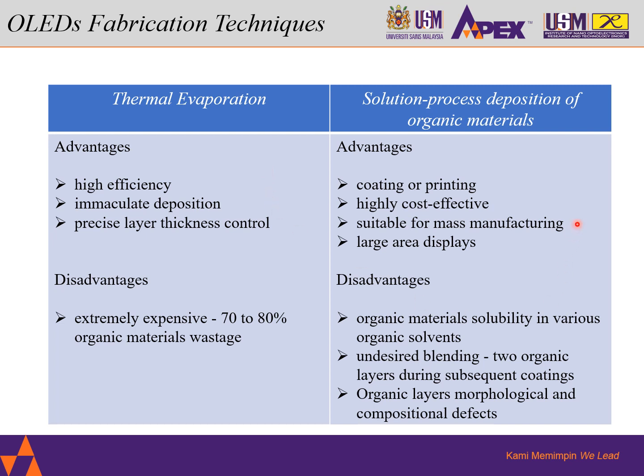The second fabrication type is solution process deposition of organic materials. It uses methods like coating or printing. So any fabrication process that involves coating or printing is highly cost effective and suitable for mass manufacturing, and also allows large area displays. However, the problems with this method are the solubility of some organic materials in various organic solvents, the undesired blending of two organic layers during subsequent coatings, and the morphological and compositional defects in the organic layer itself.